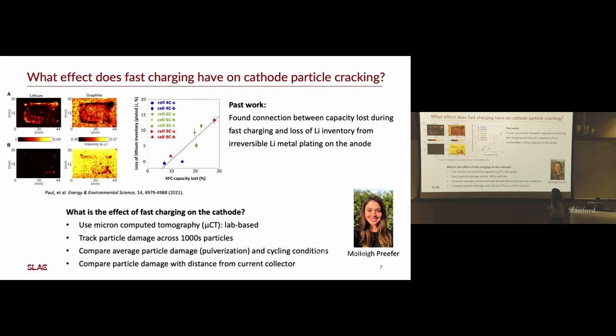And we use the lab one because of accessibility and also because the energy is higher. So you have fewer photons, but they're higher energy photons. So they can go through the material more easily. And the experiment takes longer because you have fewer photons. But in the end, if you're patient, you get the same results. So we were able to track thousands of particles, and we're comparing basically the pulverization of those particles with the cycling conditions we have.